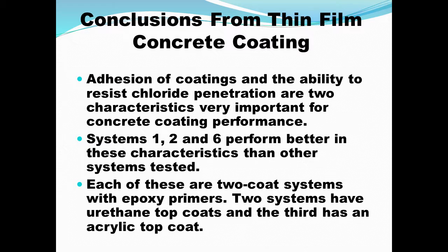So quickly, from the conclusions from this, first of all, adhesion and the ability to resist chloride are two important characteristics for concrete coating performance. Systems 1, 2, and 6 performed better than the other systems in those performance criteria. And each of those systems that performed better, 1, 2, and 6, all of them are two coat systems. Each of them has an epoxy primer. Two of them have urethane top coats, and the third has an acrylic top coat.